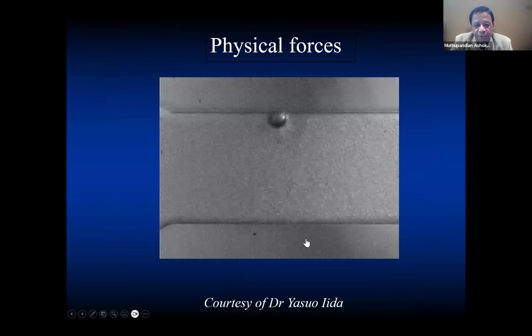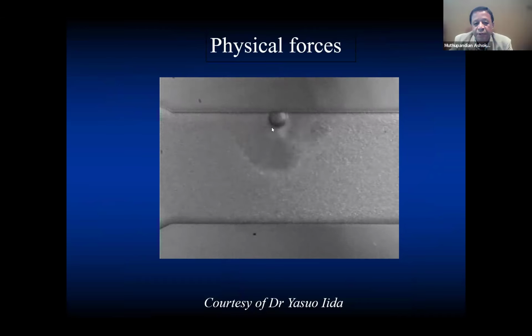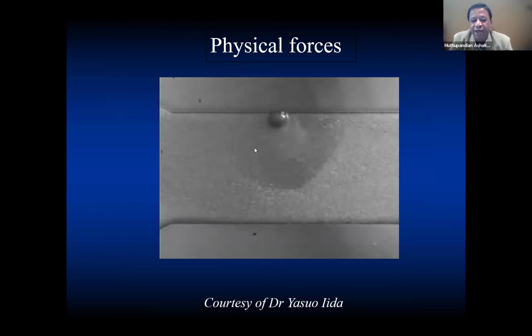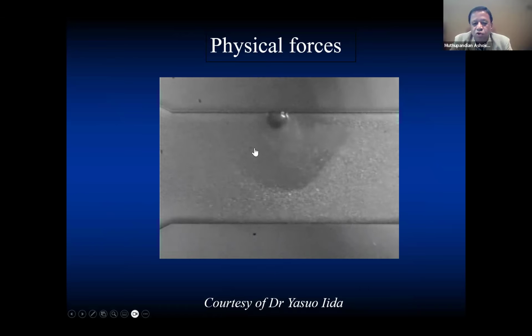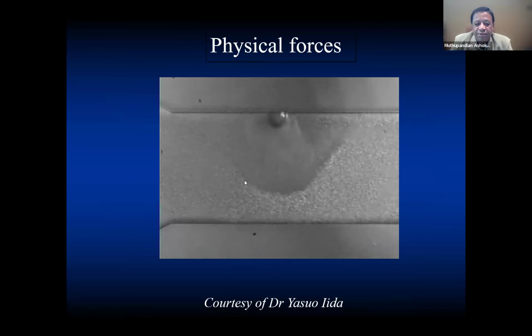I'm hoping that you'll be able to see this video clip that I'm playing. What we have here is a bubble trapped in a capillary, and that bubble is oscillating, driven by a transducer at the bottom. This capillary tube is about 400 microns in diameter. You can see how strong the shear forces are around the bubble when the bubble is oscillating. Here we have some silica particles that are moving around.